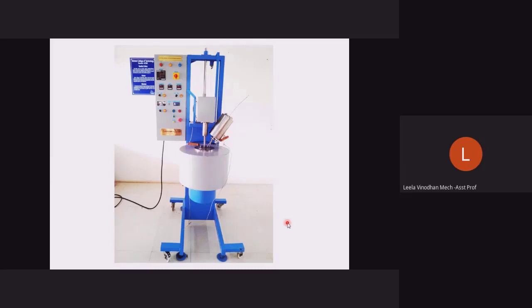And moreover, when you are going for magnesium casting, as long as you keep it inside the furnace, the furnace temperature also will increase. Even if you are trying to keep the furnace temperature at 850 degrees Celsius or 900 degrees Celsius, it will increase further. As long as you keep the magnesium inside the furnace, that also is going to add some heat to the furnace. Because the reinforcement that you are going to add to the magnesium, at certain times, will have an exothermic reaction. So that is going to give you additional heat. So in those cases, we have to maintain it.